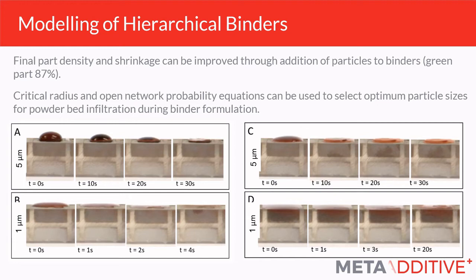You can see from the bottom B and D here, when the particles in the binder are smaller and lower than the critical radius of the powders in the powder bed, we see that we start to penetrate through that powder bed, and that hopefully will give us an optimised density and lower this shrinkage rate that we see.